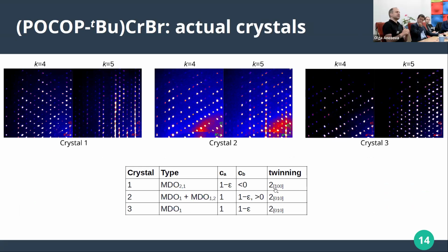So that makes life a bit more difficult if you want to quantitatively evaluate the thing, because then you have to simulate the diffuse scattering, but then you have to overlay the diffuse scattering of 2 twin domains, right? And then it could be that the actual parameters of these two twin domains are different. So it's quite difficult.